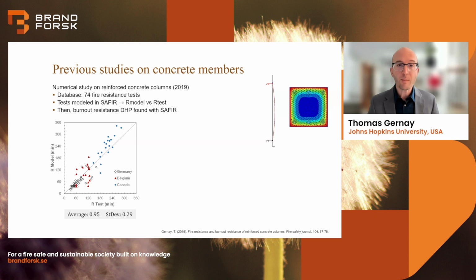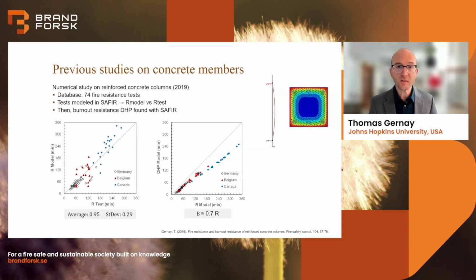So in the second step, we modeled those same 74 reinforced concrete columns with the iterative procedure that was mentioned to evaluate their burnout resistance. And the results are plotted on the right. As you can see, there was an almost linear relationship between the burnout resistance and the fire resistance. And the coefficient was around 0.7 or 0.72 between the burnout resistance and the standard fire resistance.